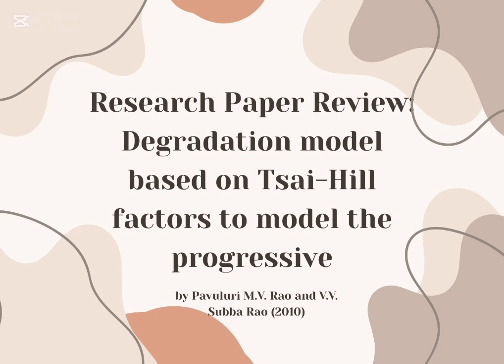To summarize, Rao and Rao's 2010 study introduced a progressive degradation model based on Tsai-Hill factors that accurately predicts how fiber metal laminates fail under different loading conditions. The model accounts for the nonlinear plasticity of aluminum, the anisotropic behavior of glass epoxy layers, and the interaction between them. Compared with earlier methods, it gives results that are closer to experimental data, while being simpler and computationally efficient.